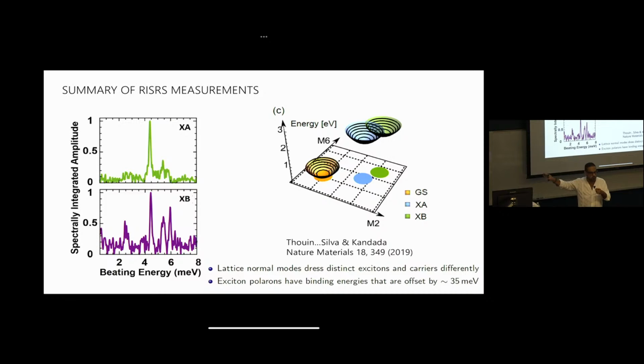What is the mechanism? What is the role of these phonons in mixing exciton A and exciton B states to permit that radiationless transition from one state to the other, to produce your emissive state in your LED? Turns out that these phonons, M2 particularly, is not what we would call a spectator. It's not just that you've excited this phonon and it happens to couple through the exciton, and that's the end of the story. They're active in driving the electronic relaxation from exciton A to exciton B. That's a very important consequence of the fact that they're exciton polarons. That character would very strongly impart the relaxation, the electronic dynamics in the system.